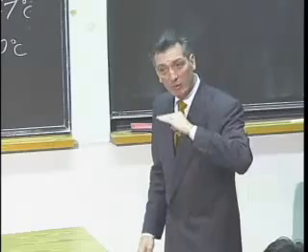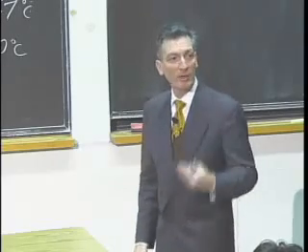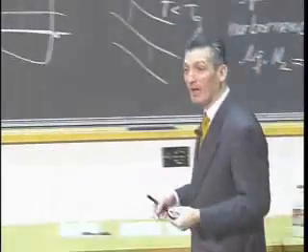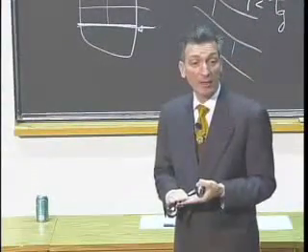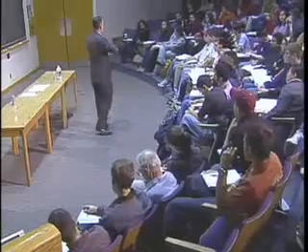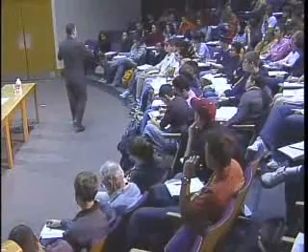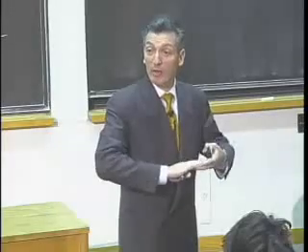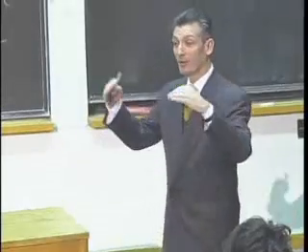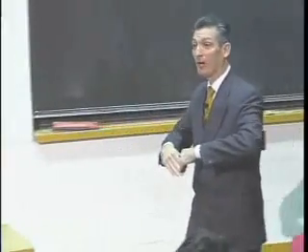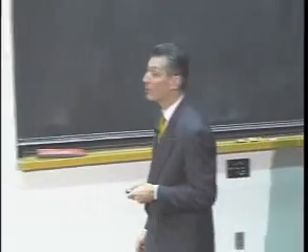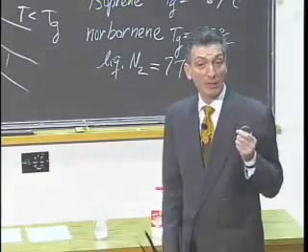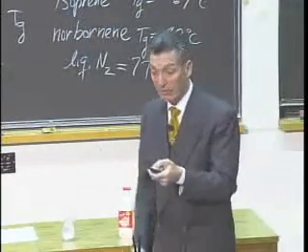But if you try to spin too quickly, you get shear dependent behavior. It's peculiar with long chain molecules. What happens is, at very, very high shear rates, the molecules won't slip fast enough, and they essentially behave as an elastomer. So at very high shear rates, instead of seeing the vortex trough, you see quite the opposite. This is called the Weissenberg effect, and it has to do with the inability of the molecules to move quickly enough over one another.